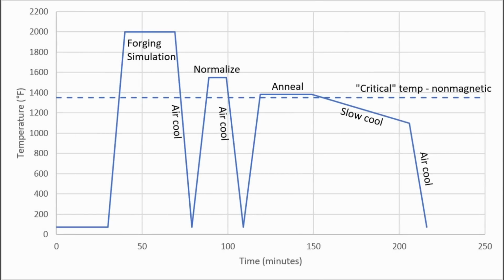To summarize the heat treatment with a furnace, you should normalize at 1550 to 1600 for 10 to 15 minutes and then air cool. You anneal at 1385 for 30 minutes and slow cool to 1100. I use 300 degrees per hour, and that should work for these steels. You do not need a grain refinement step. The anneal effectively does that.